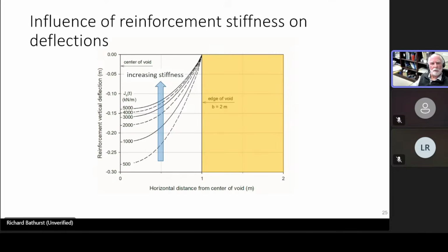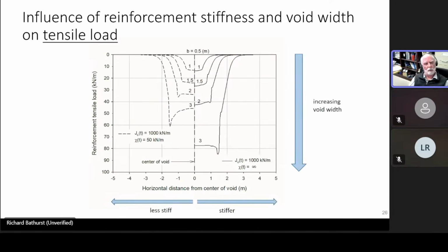This slide here is looking at the influence of reinforcement stiffness and void width on tensile load. And what we did in our presentation here is we looked at two different cases. One case on the left is with a relatively low stiffness reinforcement, and on the right, a relatively stiffer reinforcement. Because the problem is symmetrical, we can show two cases at the same time.